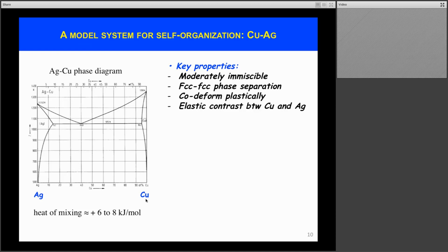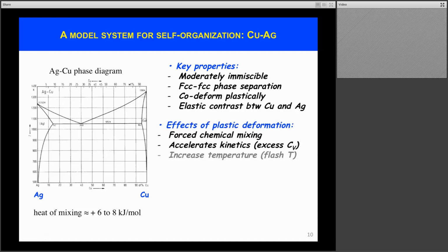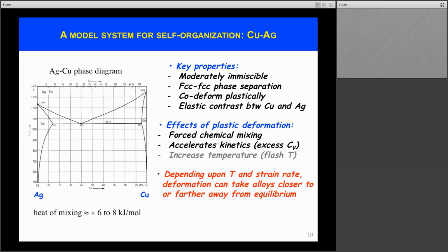These two nearly pure phases are face-centered cubic. And when we subject this system to plastic deformation, because of the similarity of the properties of copper and silver, particularly their similar, not too different lattice parameter and elastic properties, they will co-deform. And so during plastic deformation, what we are going to see is that this co-deformation can force the mixing of copper and silver. On the other hand, plastic deformation also creates defects, including dislocations, but point defects as well, vacancies. And so plastic deformation can be used to accelerate thermally driven kinetics. And I will illustrate this one more carefully on the next 3 slides or so.